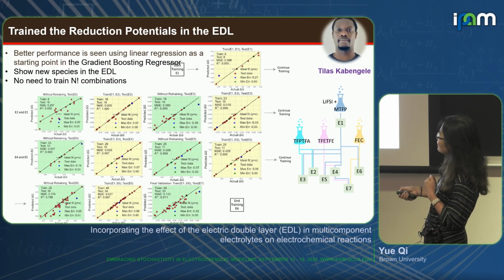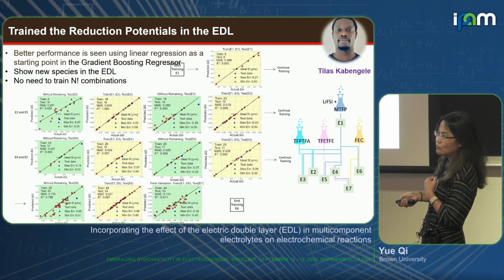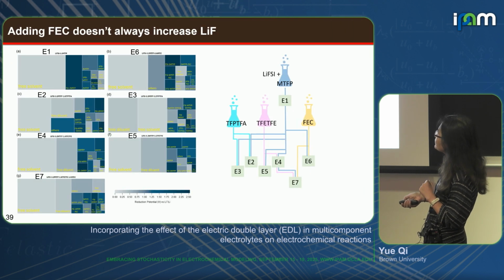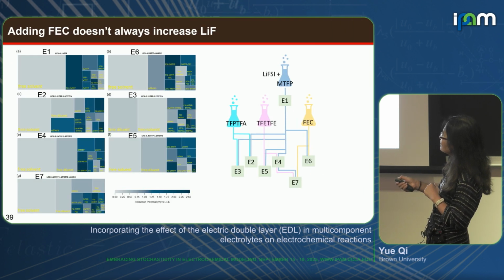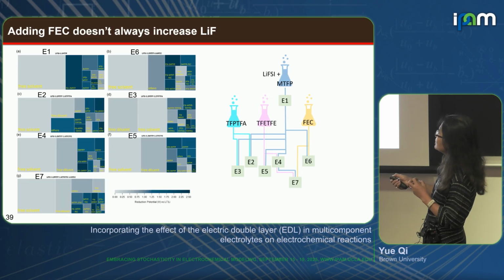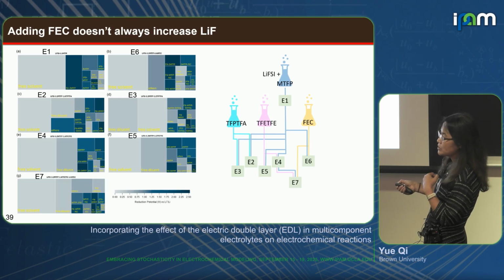So overall, after a few trainings, I think we can predict the most complex electrolytes, with a few 1, 2, 3, 4 mix. It seems to be working, and I think the reduction voltage is not very sensitive to all these compositions, but a little bit more sensitive to one or two chemical natures. That means that when we calculate our reduction voltage, in this heat map, the area means the percentage of those species, the color means their reduction voltage from high to low. And so the reduction voltage is important, and this percentage is really important.